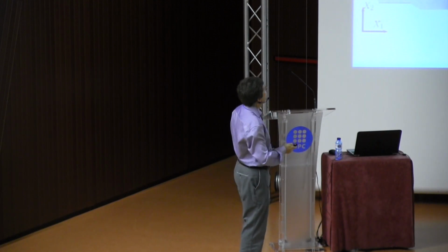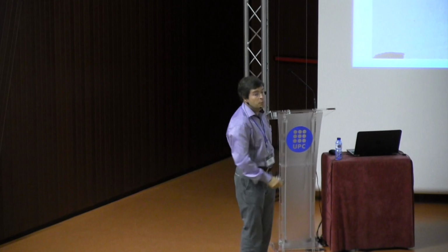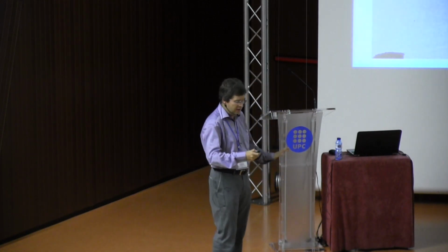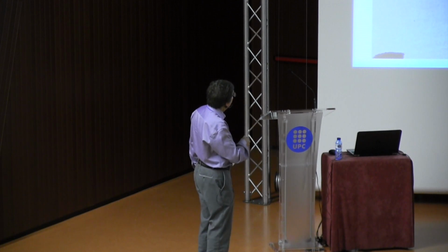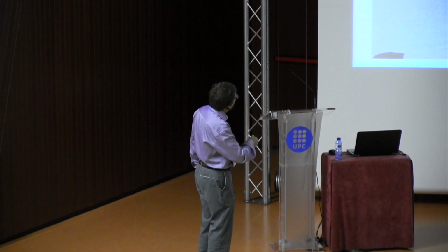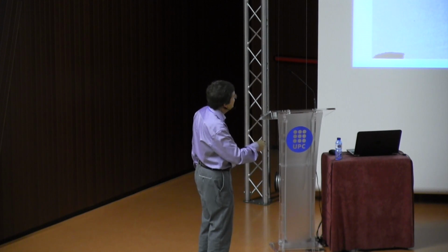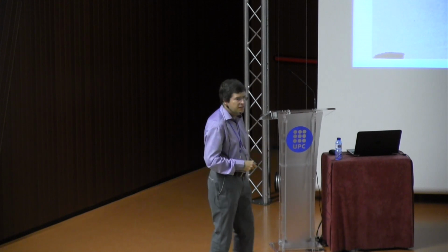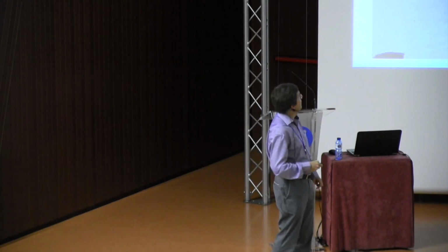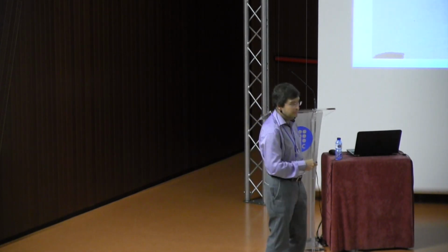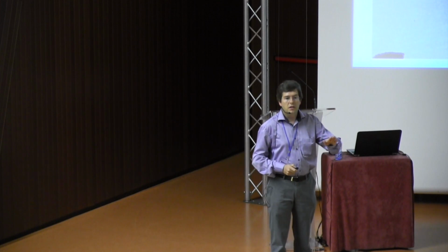If you perform some cycles now, so fatigue, in fact, you will observe the very complicated propagation of the crack. So this is really a nightmare. The crack front was here. You have first some bifurcation, you have some branching, you have hesitation of the crack, and mainly this zigzag progression. And if you look at the planes here, they are crystallographic planes.